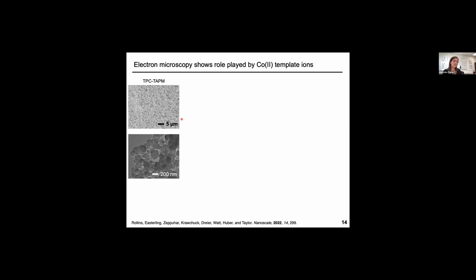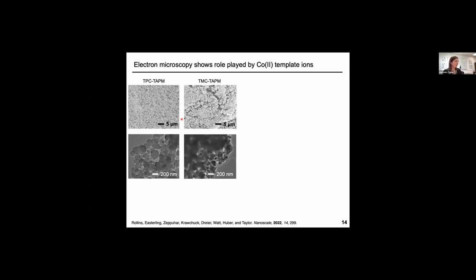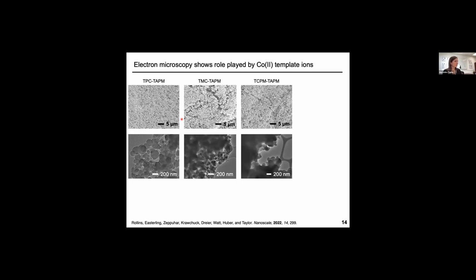These are SEM and TEM images of the three non-templated controls. You can see that we've named them according to the tetraamine and whichever coupling partner it was with. This one in the middle is the triacyl chloride that we ended up templating. So anyway, all these non-templated polymers just have a rough surface morphology. And when you zoom in and look at them by TEM, you see that they are composed of these nanoscale spherical agglomerated particles,